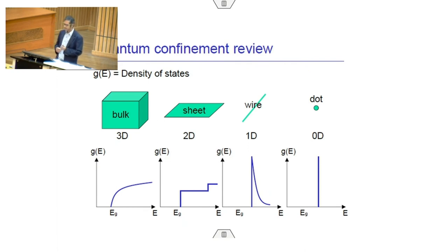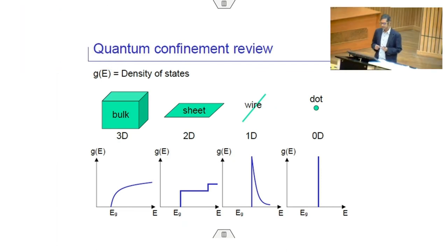So far we have been discussing electrical properties of different dimensions of nanomaterials like 0D, 1D, 2D, and 3D in isolated entities. But from the practical point of view, these materials need to be coupled to external circuits. If you want to use them, you have to connect them with electrodes. For 2D and 3D nanomaterials, this will be an ohmic kind of contact, right? There will be voltage drops. But for 0D and 1D nanomaterials, the contact resistance between the nanomaterial and the connecting leads will be extremely high, okay?